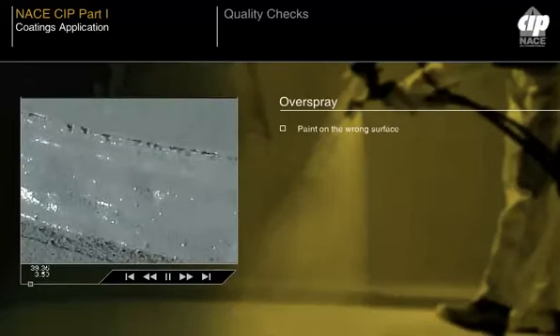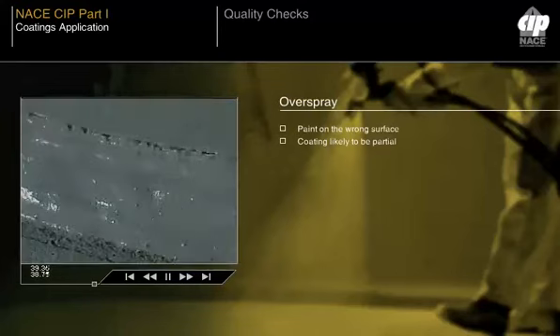Overspray occurs when the spray gun propels paint onto another surface which was not intended to be painted. This is most likely to occur when the applicator fails to trigger the gun, continuing to spray paint at the beginning or end of each stroke. Overspray generally adheres to the surface it reaches, leaving a rough surface. The main problem for the applicator is that coatings are applied to surfaces where it is not appropriate. The coating is likely to partially create a film, forming an ineffective barrier.